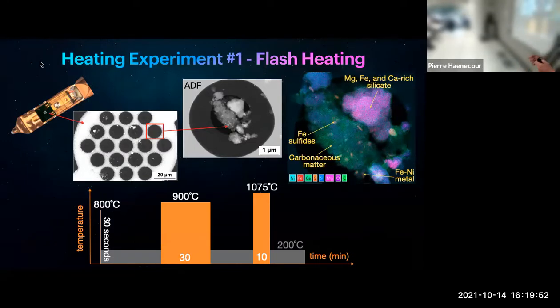The reason for it is just because as the temperature is slightly increased, it doesn't affect the material visibly, but it increases the electron yield. And so it basically gave us much better imaging. So all the imaging was done at 200 degrees. After some EDS, we put the sample back to 900 degrees for 30 minutes to see what's happening. Went back down to do more imaging, and then flash heated for 10 minutes this time at 1,075 degrees.